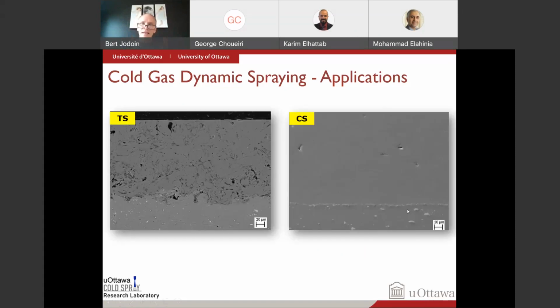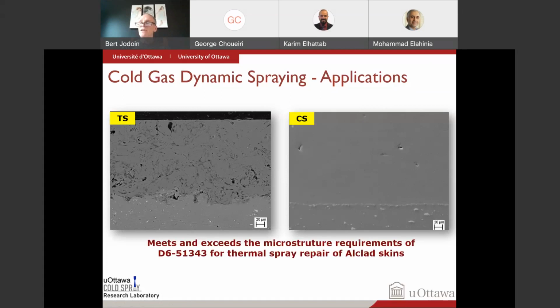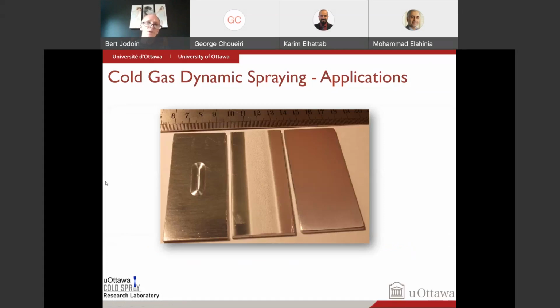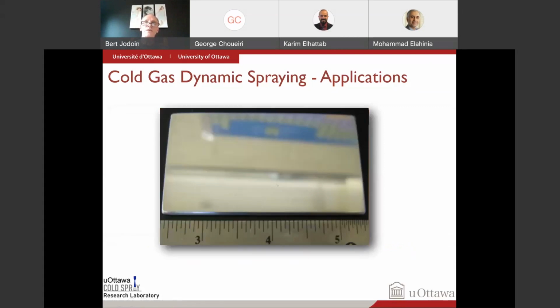So here you can see that's the original surface, and that's the cold spray coating compared to using other thermal spray processes. You can see it's a pure aluminum coating as opposed to an aluminum coating with tons of impurities in it. So the cold spray process, we've developed the parameters and application and demonstration that it can be used to repair aircraft skins, and that's actually now a Boeing internal specification that they use to repair aircraft skins. So you can see here one example where we did a damage here, and then we spray, and then we polish, and then you have the repair there. That looks great. You can't even see where the repair was.